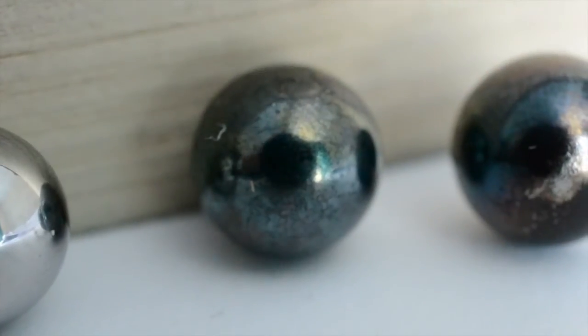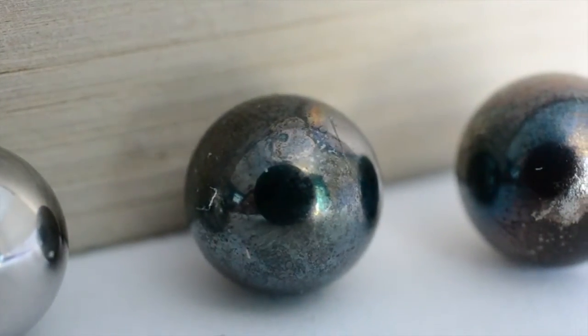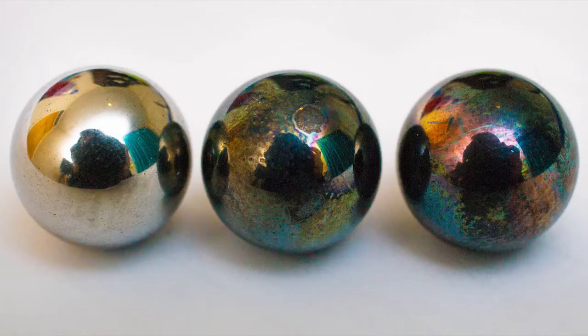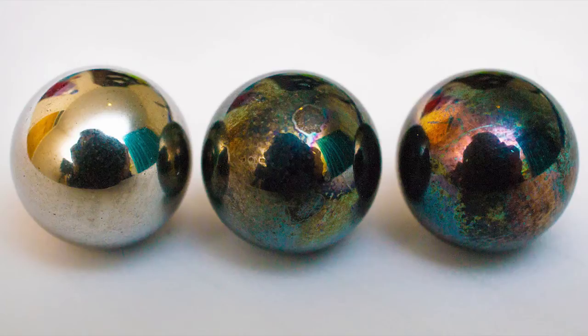Along with a myriad of other colours on their surface, these are all caused by the build up of oxides due to the intense heat. The colour depends on how thick the oxide build up is at that section. The enhanced image clearly shows the variety of colours formed by this process.